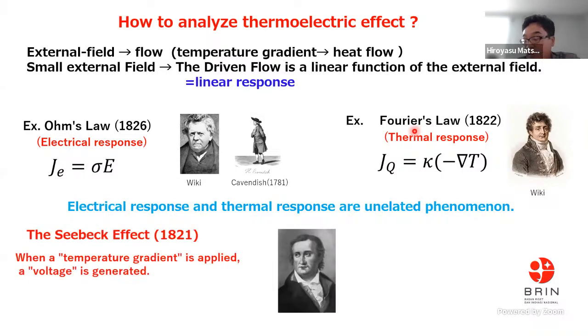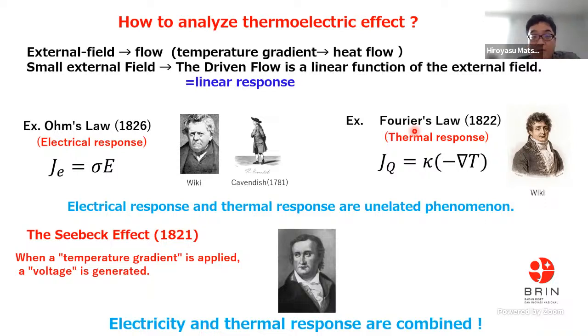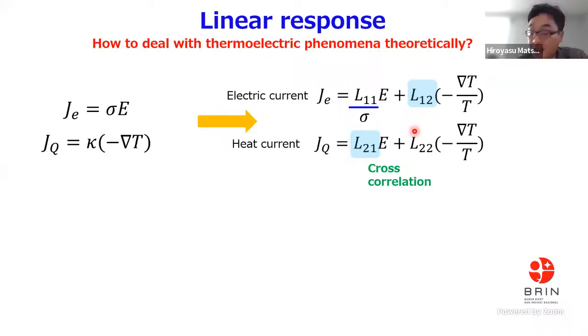But we have the Seebeck effect. The Seebeck effect is a cross effect, a combined effect. So when we discuss the Seebeck effect, we need the cross term, which means we can express these equations with the cross terms, L12. L12 corresponds to the cross terms. When we apply a temperature gradient, we get an electric field, and when we apply an electric field, we get a heat current. This is the cross correlation.